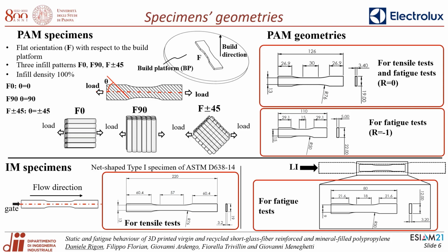For the IM specimens, net-shaped type 1 specimens from ASTM D638 were produced and used for the tensile test, while for the fatigue test, smaller specimens were machined from the previous ones to avoid buckling during the compression load in the fatigue test with load ratio equal to minus 1.